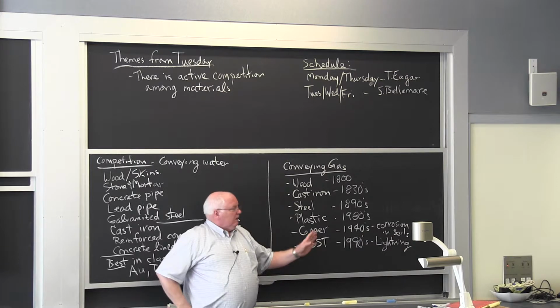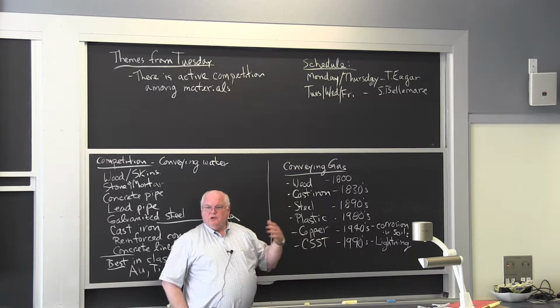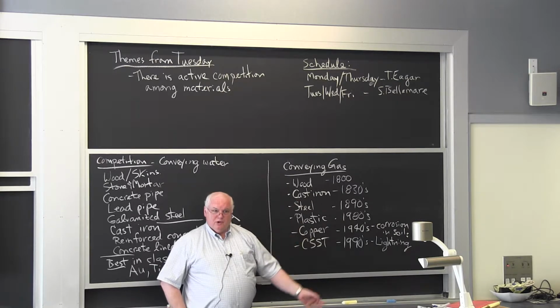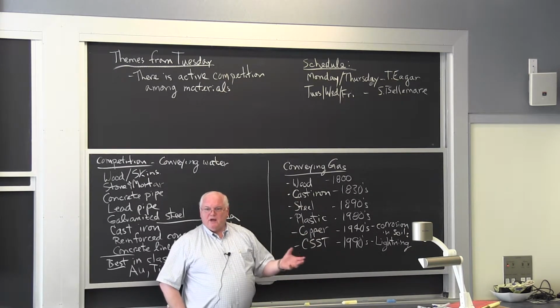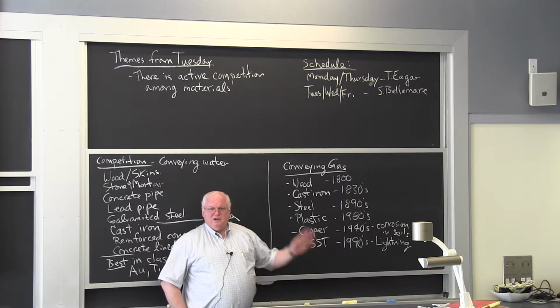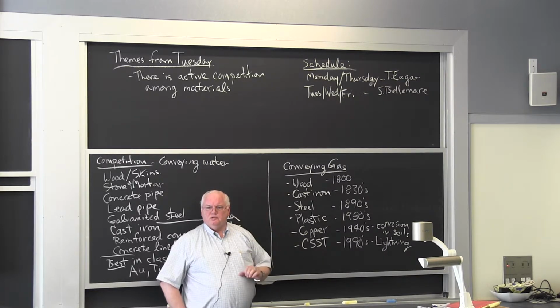And what do you do? Well, when you have an investment like that, which is a multi-billion-dollar investment, you protect it with an impressed current, an electric current, or anodes of magnesium, aluminum, or zinc buried in the ground. You make the pipeline cathodic so it won't corrode. I've seen pipes come out of the ground that are 50 years old, and if they've been adequately cathodically protected, they look like they're almost new, except for having some dirt on them. No pits, no corrosion. It's what we do on ships, okay?